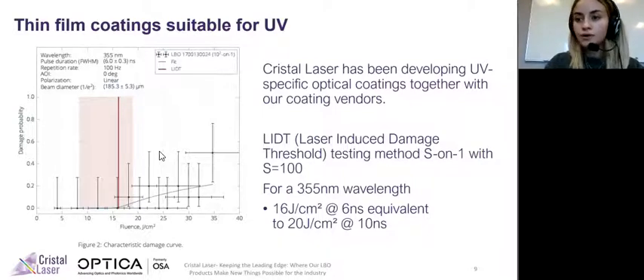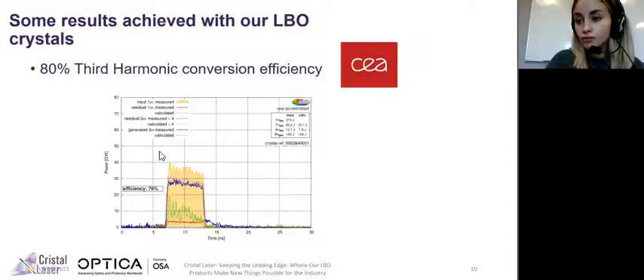So this is all for the key parameters we've identified and tried to improve through the years to enhance the lifetime of crystals under UV light. And now I'm going to conclude with a presentation of a few results that our industrial customers managed to achieve by using our crystals. For starters, we have the French Atomic Energy Commission, who reached a high efficiency of third harmonic generation with a laser of 1053 nanometers to reach a wavelength of 351 nanometers.